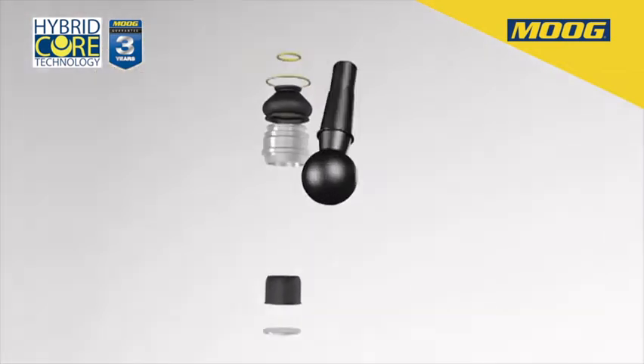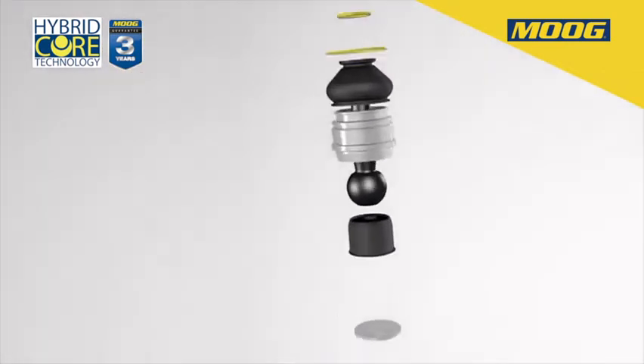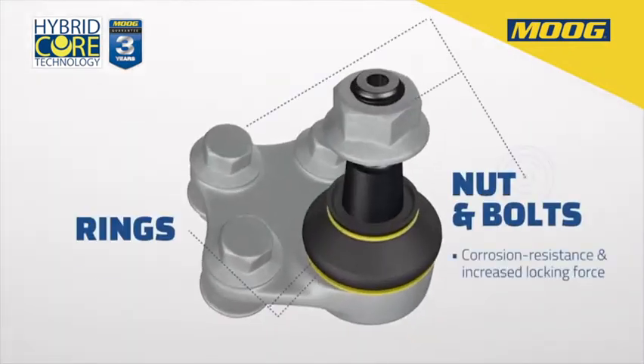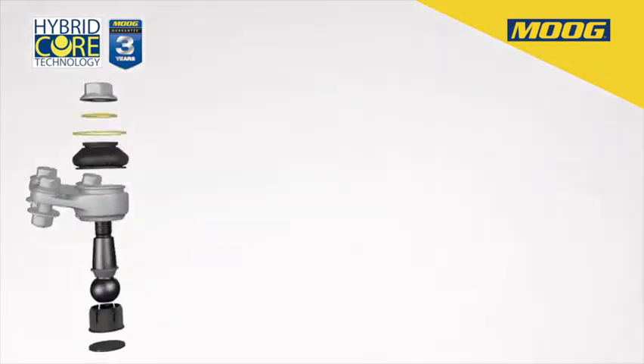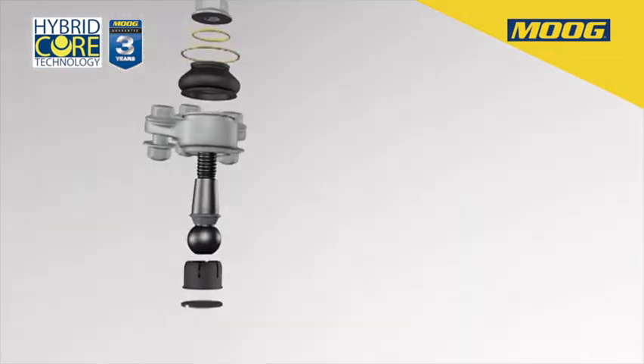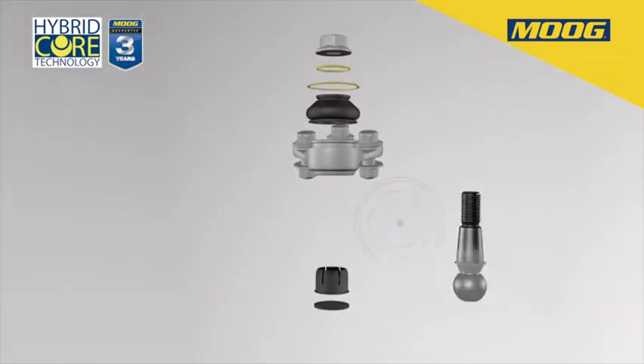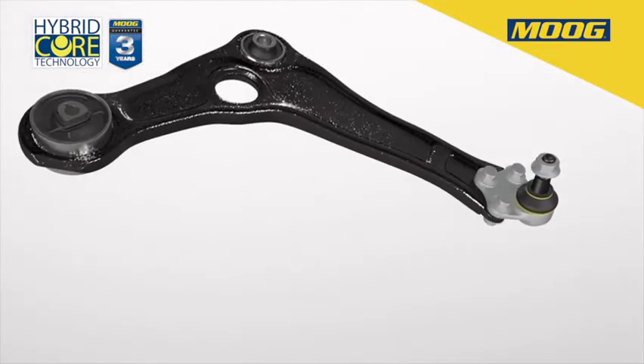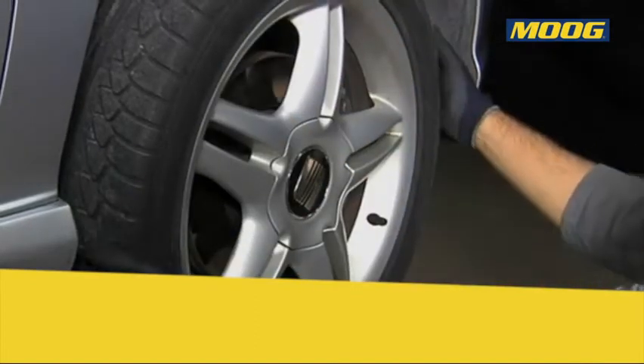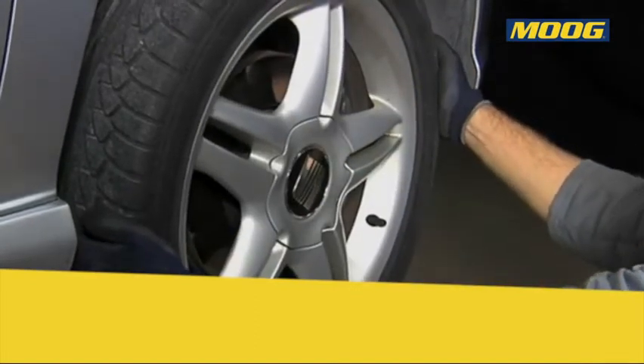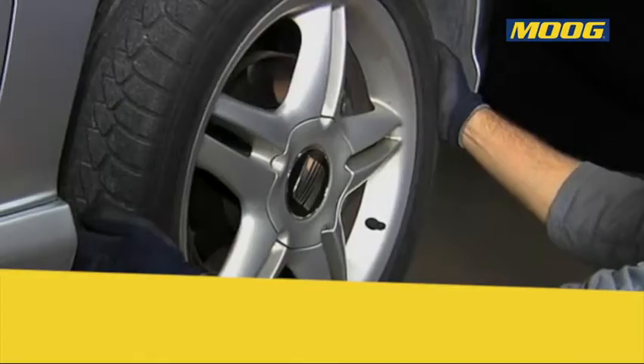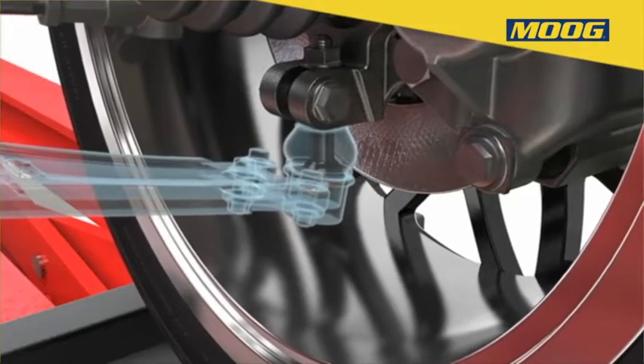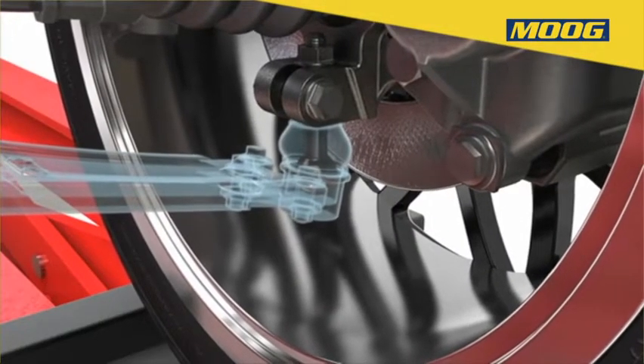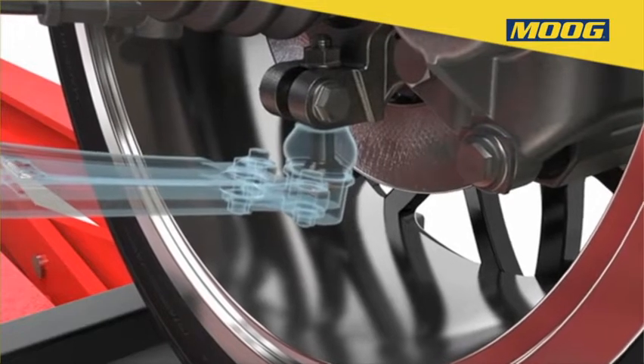This is due to the fact that the different high-intensity stresses to which the part is subjected can cause very high friction forces between its components, which end up generating premature wear of the bearing and the ball stud. This wear produces undesired play, which results in loss of precision, and therefore of control in the steering, as well as noisy operation, increasing exponentially the risk of an accident.